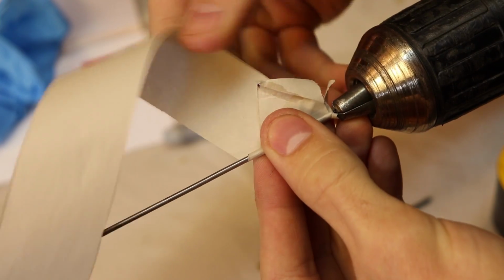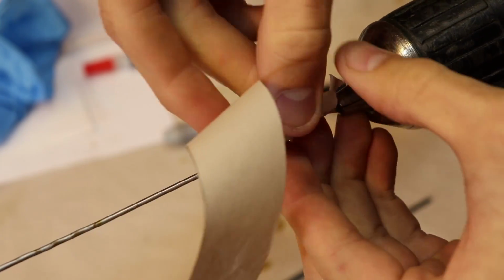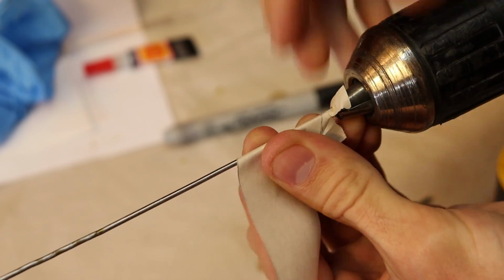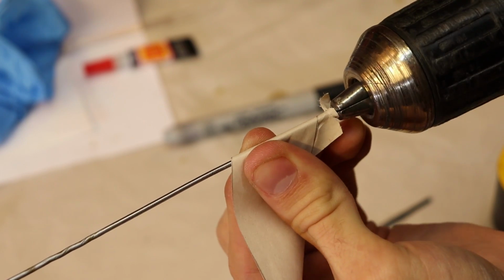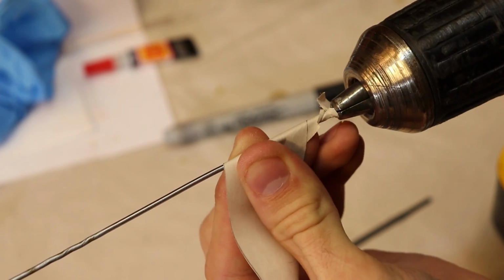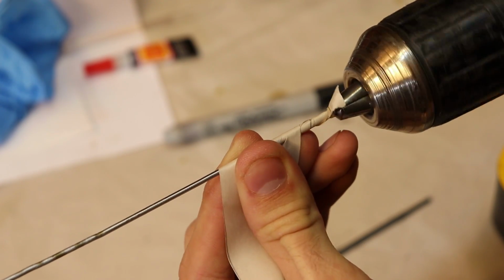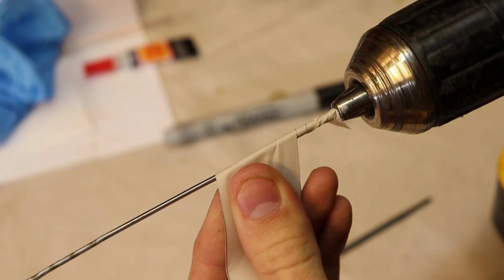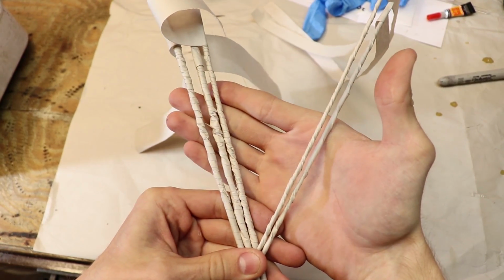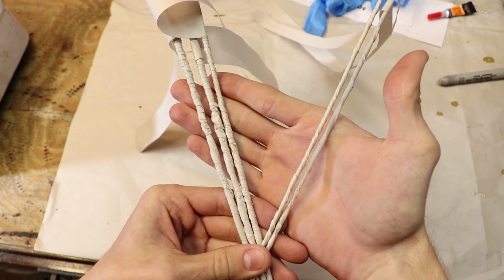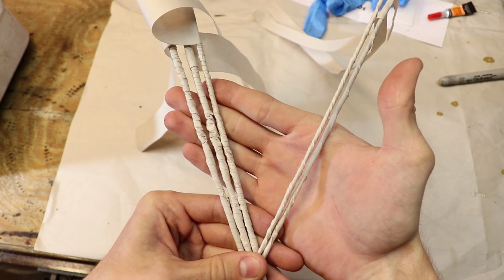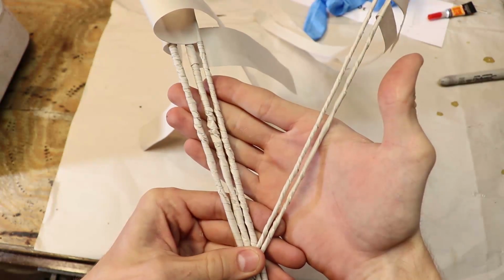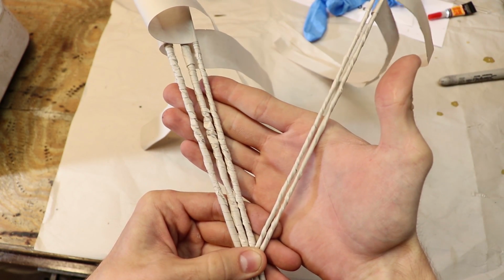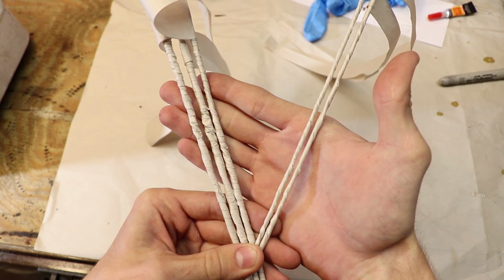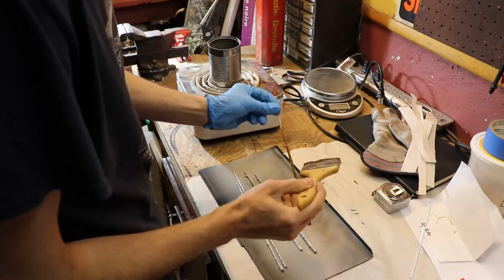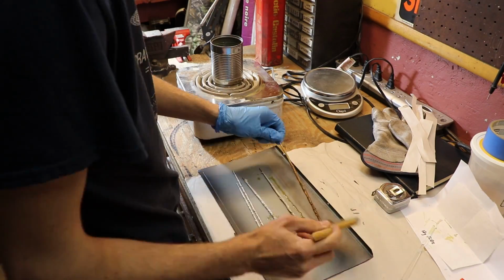Now a little side note here. I'm wrapping at about a 45 to 30 degree angle. I noticed a sharper angle gives a smoother but thinner wrap. You will just have to experiment with the technique a little bit to get good consistent wraps. So this is how they came out, and you can see the difference between the rods on the left that were wrapped in 1-inch wide strips to the nicer rods on the right, which were wrapped in 1/2 inch wide strips. Now we can begin soaking these rods in the sodium silicate.